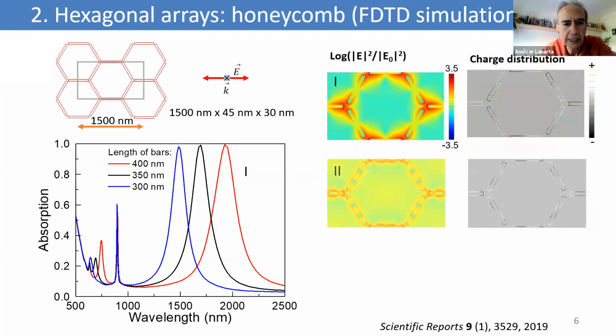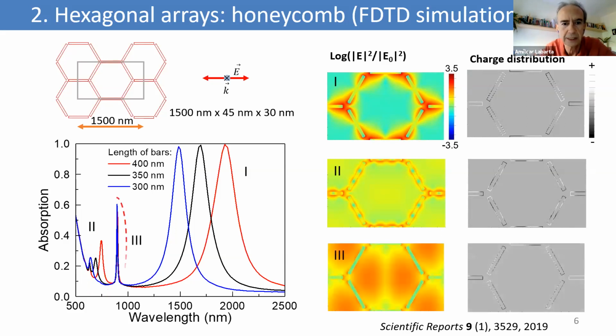The second peak related to near field interaction is this one that is labeled with the 2 letters, and this is also a near field interaction. It's a more complex interaction because we have a multipolar excitation of the bar, but essentially we have an interaction between the bars which are converging in the vertex. Okay, and let me show you what happens in the 3rd peak, the one which is related with the collective mode. In this case, the electric field is much more distributed throughout the whole surface, as you can see.